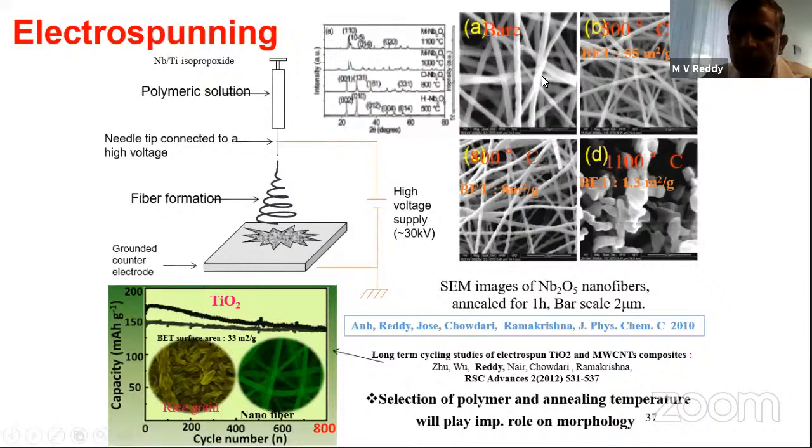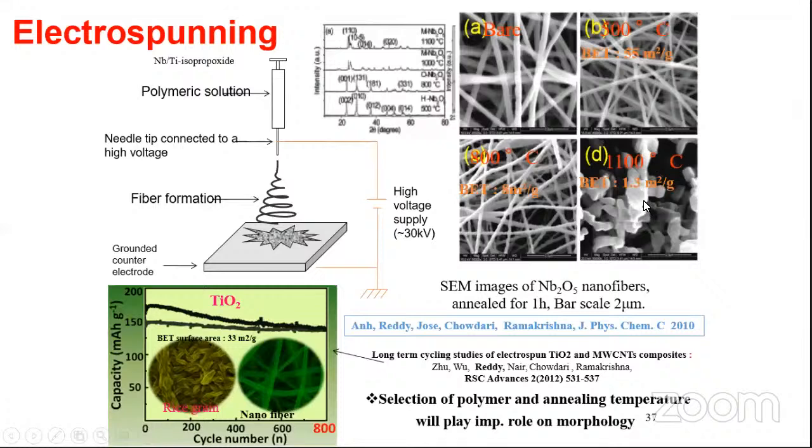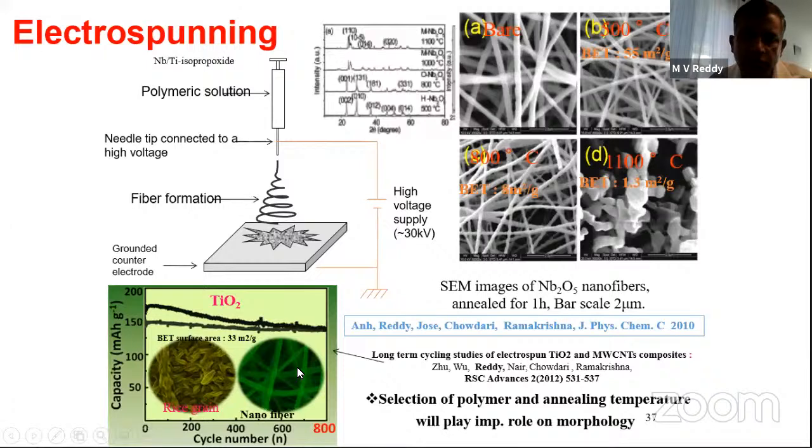In summary, this material may be really good. If you decompose the sample, with any electrospinning material near the polymer decomposition temperature, it may be good. If you exceed that temperature, you'll get almost a highly crystalline material at the end. As you can see, the particle size increases as a consequence of high temperature, and the surface area decreases. I don't claim that electrospinning is a large scale preparation, it may not be, although nowadays, depending on applications, people are looking for large scale preparation techniques.